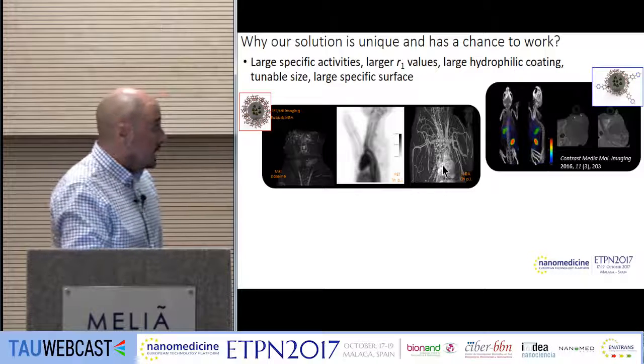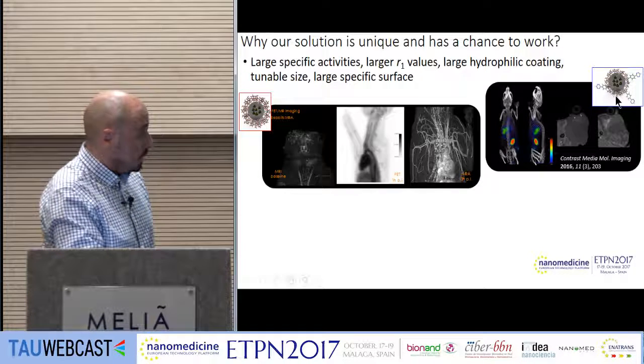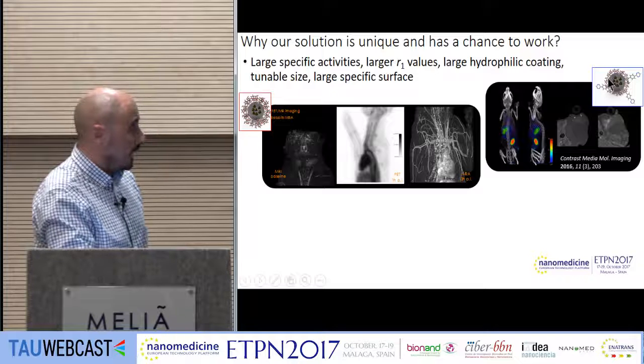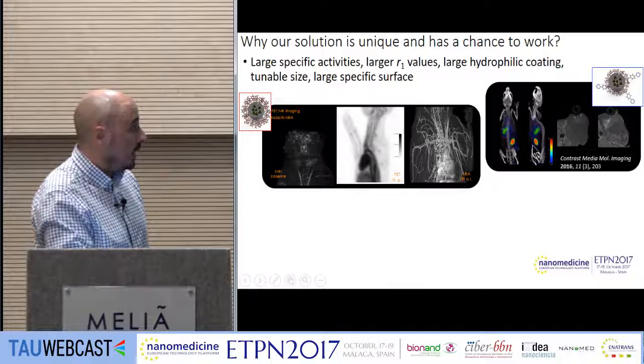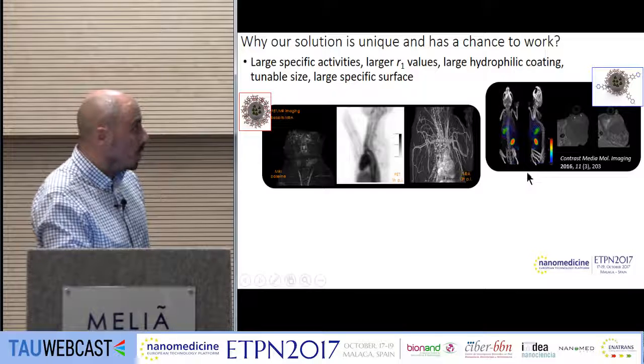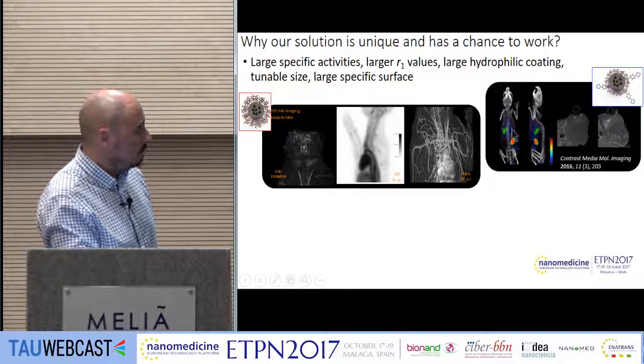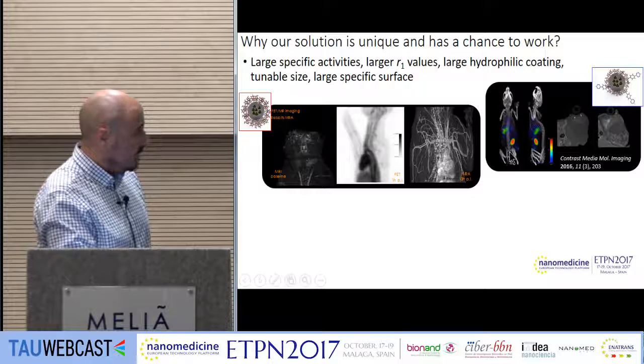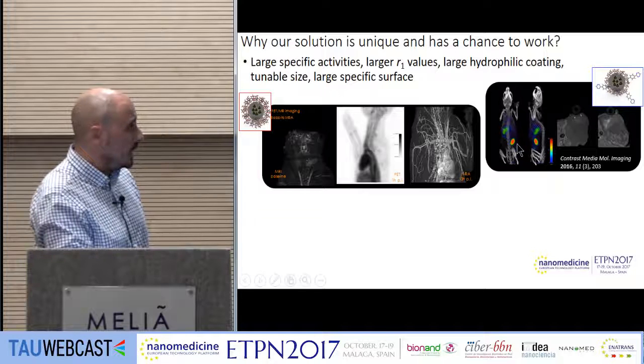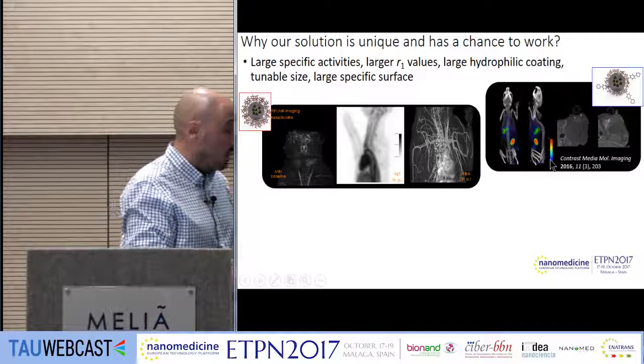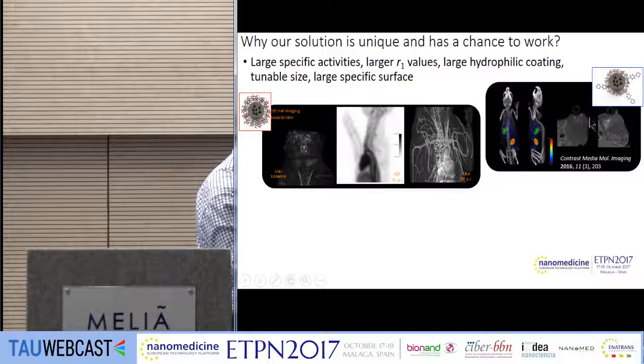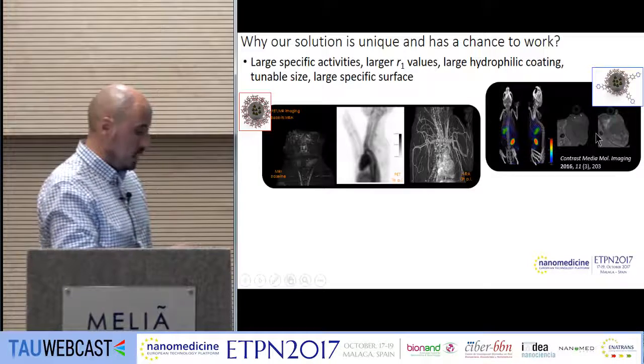You can functionalize them with a different coating and adding a peptide. In this case it was to detect angiogenesis. This is what I mentioned before. Here I don't have to tell you where you have to look to see the signal. You have a very small signal in the liver and a quite large and easy to identify signal in the tumor. But you can see also with positive contrast. This is the baseline of the tumor with no signal, and I think you can see here surrounding the tumor a positive signal, a positive contrast due to the accumulation of these nanoparticles.